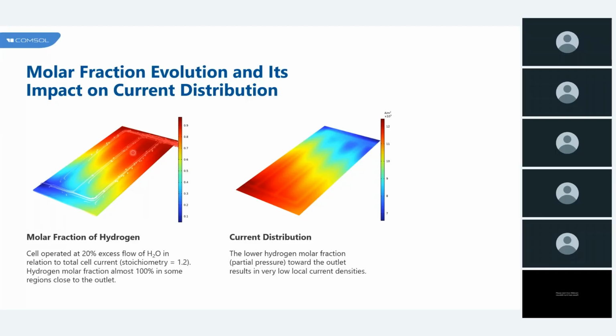So this non-uniformity of the gas composition in the electrochemical activity can lead to performance degradation, uneven thermal and material aging, and lower overall efficiency. So to mitigate these effects, both cell design and system level control must be optimized by adjusting flow field geometry, diffusion layer properties, and the reactant stoichiometry to maintain uniform operation. So this underscores the power of the detailed multiphysics simulation in COMSOL, enabling better design decisions and improving long-term durability and efficiency of the SOEC.